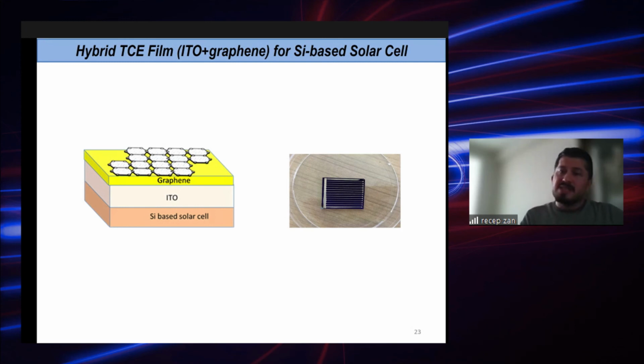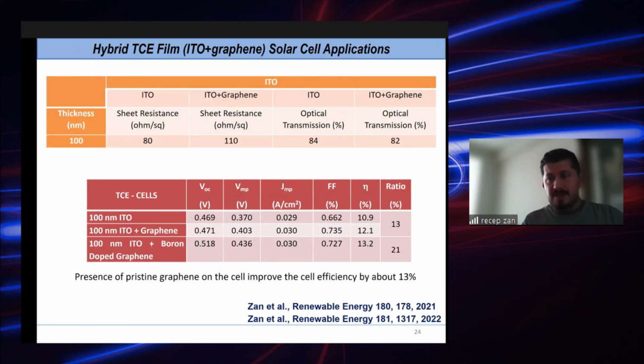And what we did, after we synthesized pristine graphene and boron-doped graphene, we fabricated silicon-based solar cells. As I mentioned at the beginning, our aim was to use graphene on top of the silicon solar cell with the ITO structure, either to remove ITO or to use them together as a hybrid structure, as a transparent conductive electrode. So in our case here, as you see, we use graphene with ITO, the pristine graphene and the boron-doped graphene. We did a similar study for nitrogen-doped graphene as well.